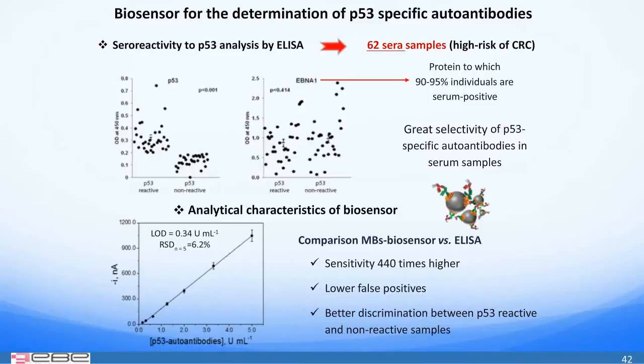The detection of autoantibodies to p53 was carried out on a non-characterized population of 62 sera from individuals in a high-risk program to develop colorectal cancer. An ELISA test determined that 32 out of the 62 analyzed sera were positive for the presence of p53 autoantibodies, with an absorbance 5 times higher than the negative control. The seroreactivity to EBNA1 protein, employed as a control, confirmed the selective seroreactivity to p53 in the analyzed population. Under the selected experimental conditions, the calibration plot, constructed with a commercial standard, demonstrates that the sensitivity of the biosensor is 440 times higher than the ELISA methodology, which allows a better discrimination between p53 reactive and non-reactive serum samples.